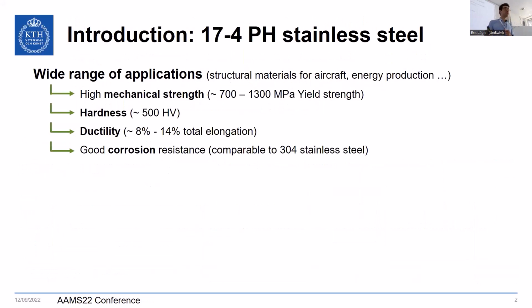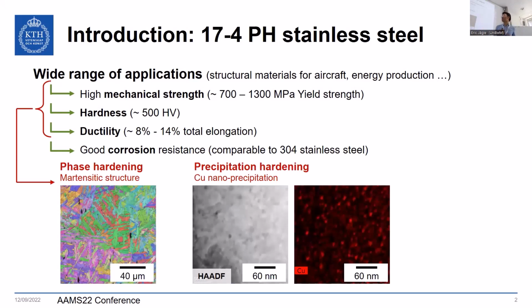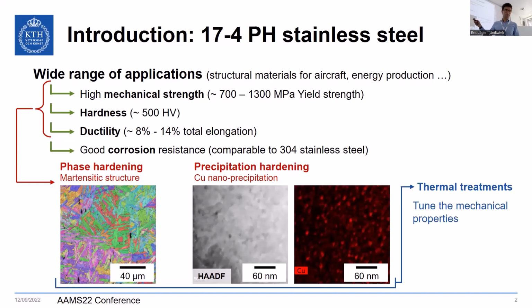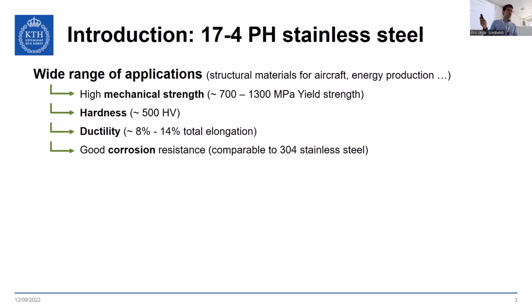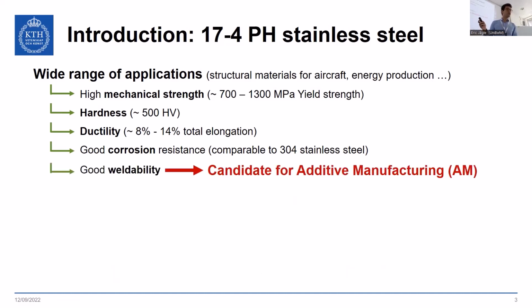So for a short introduction of the material, this 17-4 PH stainless steel has a wide range of applications due to its relatively high mechanical strength, hardness, and ductility, while keeping a good corrosion resistance. These mechanical properties are mainly due to their microstructure, of course, with the phase hardening of the martensitic structure and precipitation hardening coming from copper nanoprecipitates. Those mechanical properties are tunable, especially in conventional processes through precipitation hardening. Another interesting property of these materials is good weldability, which makes them good candidates for additive manufacturing.